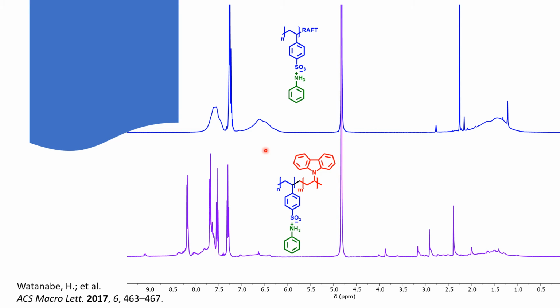Comparing the proton NMR spectrum from the macro-RAFT agent to the block copolymer, we can observe the presence of new aromatic signals, which correspond to aromatic protons from the carbazole substituent. These signals overlap with protons from anilinium and styrene sulfonate. Nevertheless, the integration of all these confirmed the presence of anilinium styrene sulfonate and vinyl carbazole in the structure of the copolymer. Also, we can observe the presence of aliphatic protons from the backbone.